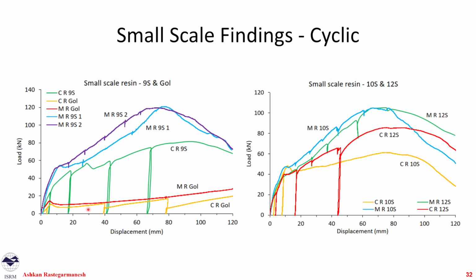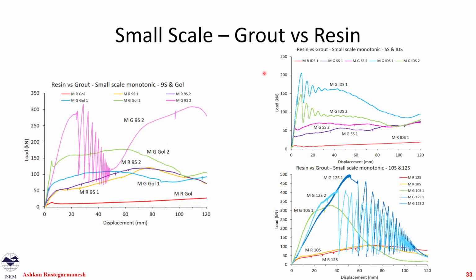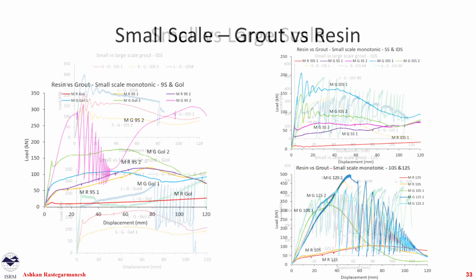For our cyclic tests, as we can see, the cycles are now much more spread apart compared to the larger scale, which was mostly in the beginning of the test. Now we have much more displacement, with a gap between each of our cycles. The difference between grout and resin for our smaller scale test, as you can see here, is that our grouts are again superior. We are getting much higher load values compared to our resin values, which are much lower.